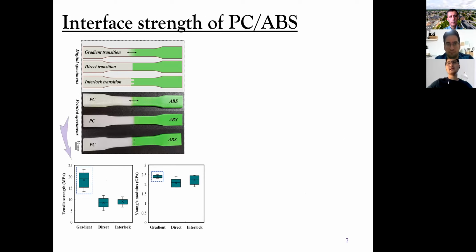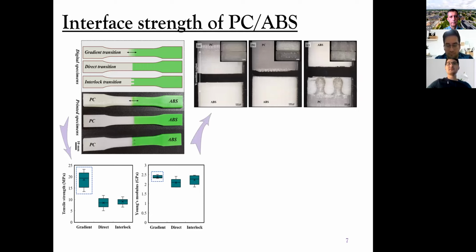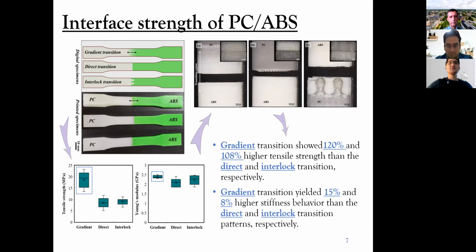Since the material transition occurs gradually in FGM made parts, the gradual transition helps to reduce stress concentrations at material interfaces. However, the abrupt change of material properties in direct and interlock patterns increases the stress concentrations, and therefore delamination occurs at the interface. So the gradient transition showed, according to the results, 120% and 108% higher tensile strength than the direct and interlock transitions respectively. And the gradient transition yielded 15% and 8% higher stiffness than the direct and interlock transitions.